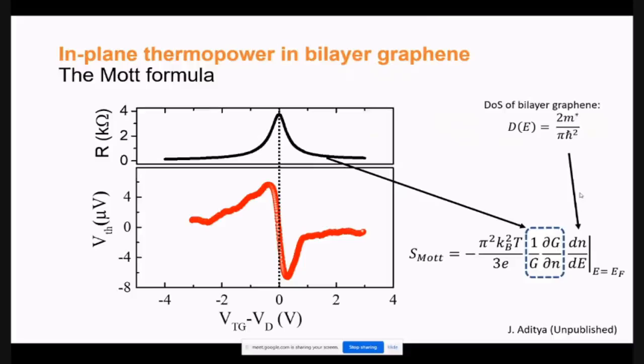Okay. So this is an example. This is data of Aditya Jayaraman, who is about to finish his PhD, and hopefully this paper is going to come out soon. So this is a typical graphene. I mean, this was taken in a bilayer graphene, but there is nothing special about bilayer graphene here. In this case, you can see that this is R versus Vg, or the density of bilayer graphene. And this is the corresponding thermal voltage measured by applying a temperature difference across the two layers, okay, across the graphene layer.